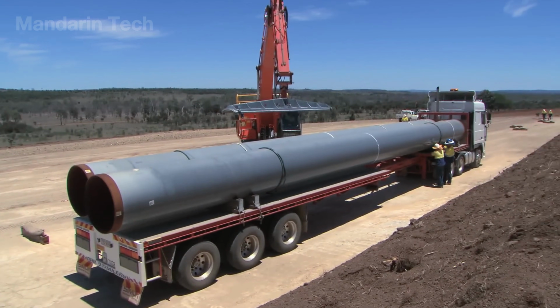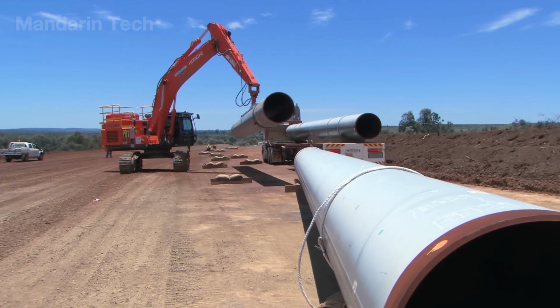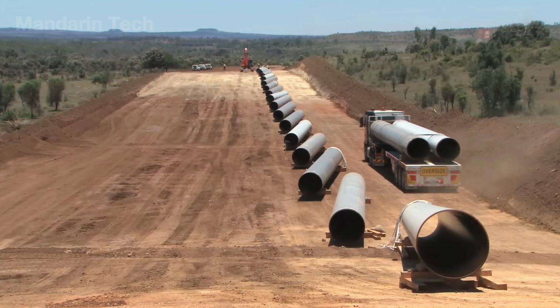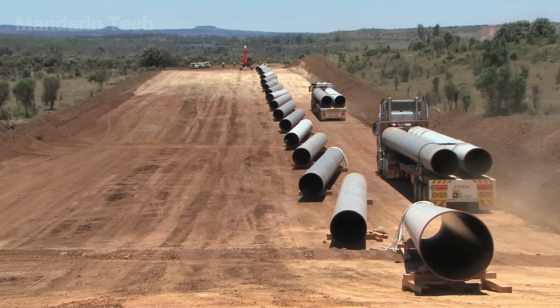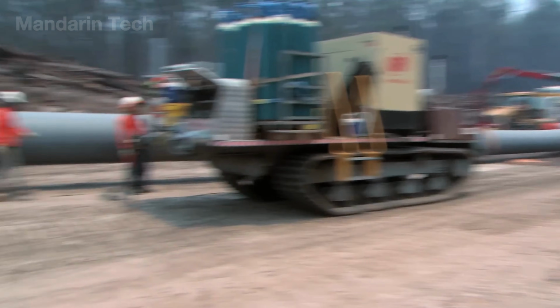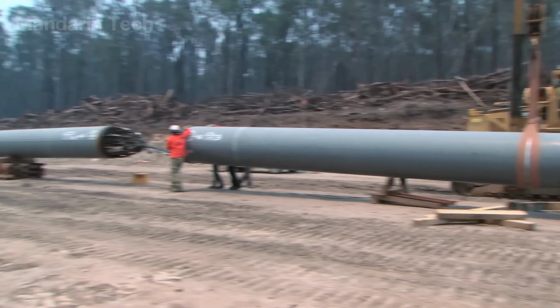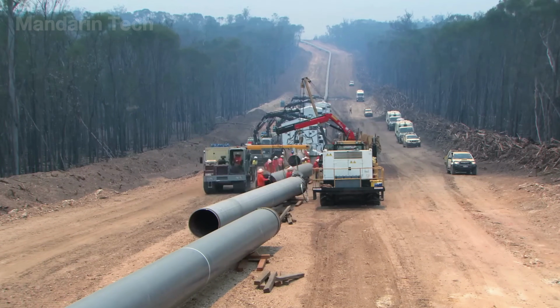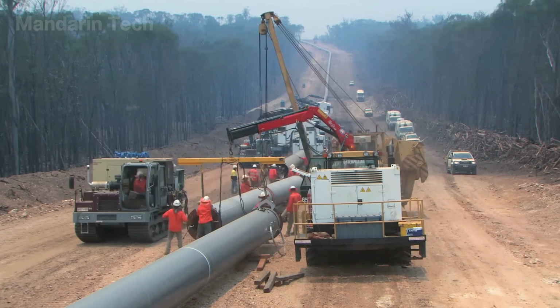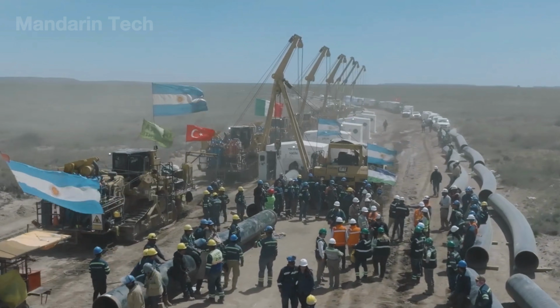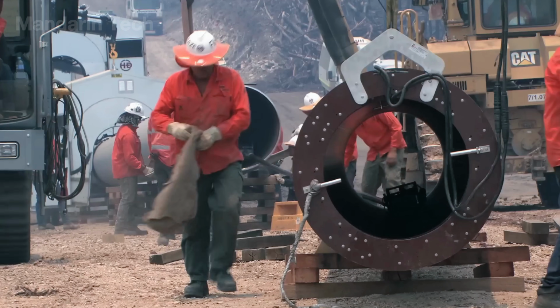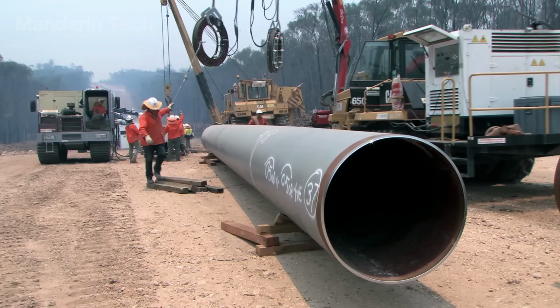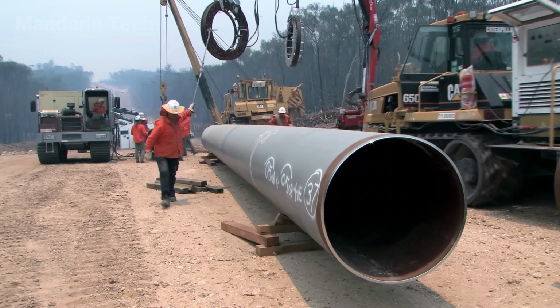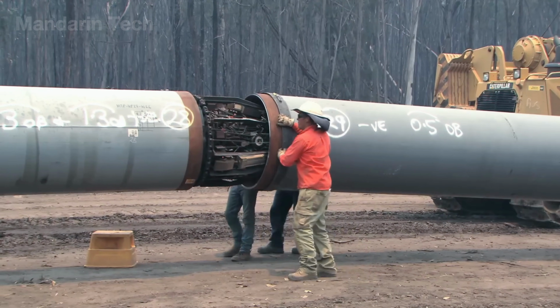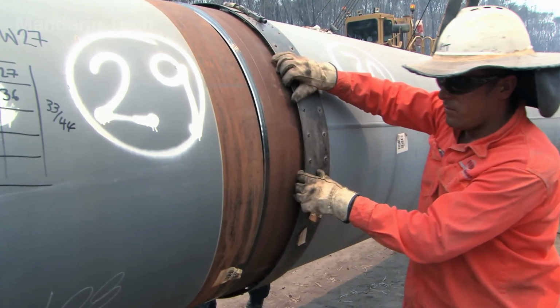To build large diameter pipeline corridors, a construction zone roughly 40 meters wide is prepared ahead of time, enabling the full installation sequence to move forward without interruption at an average rate of about 1.5 kilometers per day. Pipe segments approximately 18 meters long are chosen to limit the total number of field welds, while at the same time placing very high demands on lifting operations, transport logistics, and precise alignment during construction.